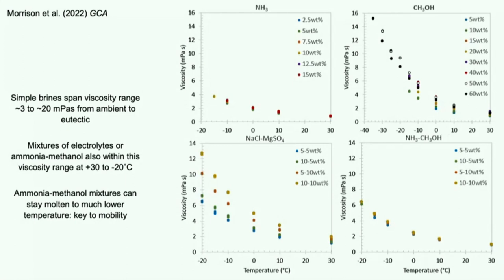If we add in methanol and ammonia, we can mix them, although that would extend the potential temperature range at which they're still molten to much lower temperatures. I can't reach them in my viscometer. But the actual effect on the viscosity is very much within the range of the other electrolytes, so we could potentially just project down temperature.